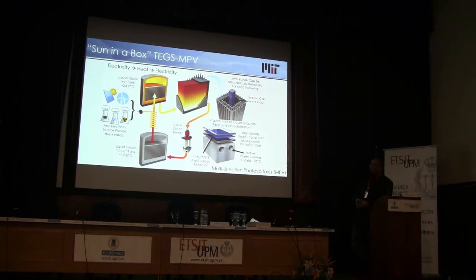In order to prevent that, we have some ideas on how to prevent that. But one of the key things that goes with that is to put tungsten here, which has about a 2 order of magnitude lower vapor pressure than graphite does. So you want to get a running start and offset the system towards not having this problem happen by using a material that's got even lower vapor pressure than graphite, which tungsten is one of the best. I believe it is the best, or lowest vapor pressure. And it's essentially the best we can get at an industrial scale to buy tungsten foil. So all our cost estimates and things have this cost included.